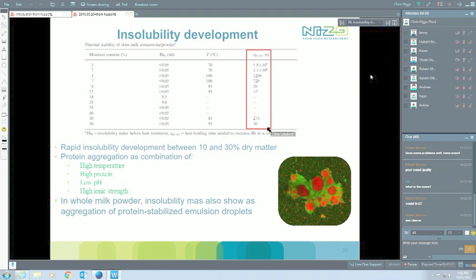And when we look at insolubility from this perspective, we need to distinguish. If we do it in skim milk, then it's nice. It will all sediment to the bottom. We get a sediment there, and we call that insolubility. If we do it in whole milk or also in infant formula or any systems that contain quite a bit of fat, then it's not just a sediment. It's also particles floating on top. It's particles sticking to the side of the wall. And when you put them under a confocal microscope, you can start seeing that the insolubility is really a protein matrix with also destabilized fat, in red, in there as well. So all that coagulates, and that may stick to the wall, that may, if it's dense enough, sink to the bottom. If there's a lot of fat in there, it may also float on the top. That's how we typically see insolubility manifesting itself in products.